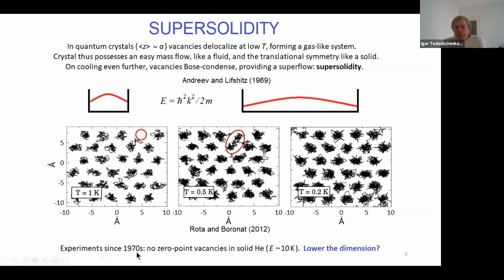Since the 1970s, there have been intensive studies in order to observe supersolidity, to observe zero-point vacancies. Unfortunately, in 3D solid helium, no zero-point vacancies have been observed. And moreover, the energy has been calculated by many methods to be of the order of 10 Kelvin. So below 1 Kelvin, there is an exponentially small number of vacancies.